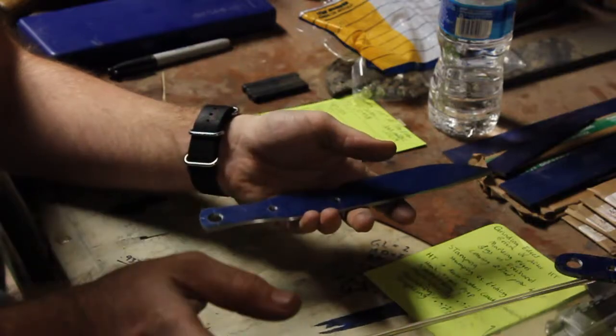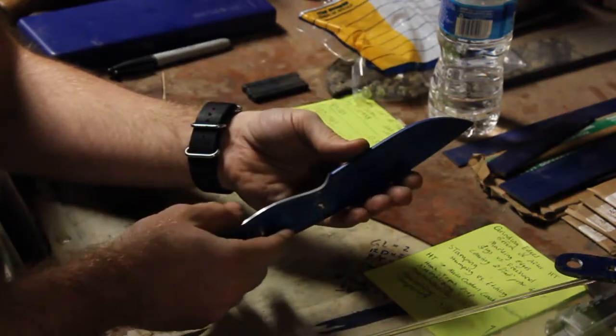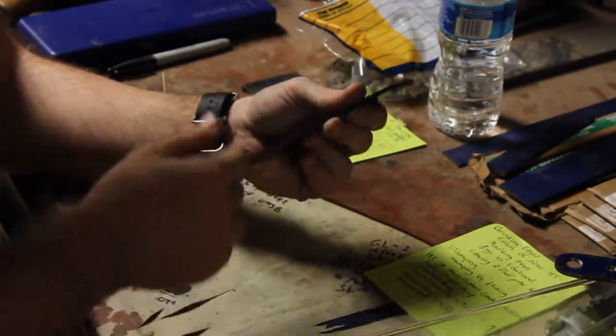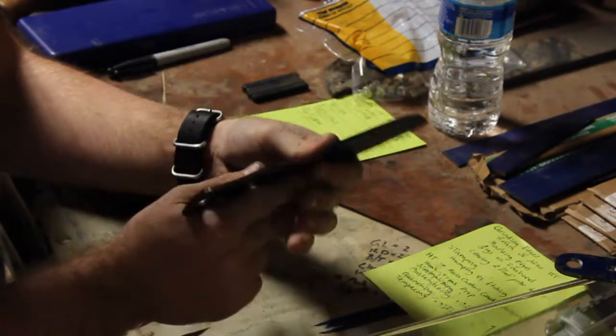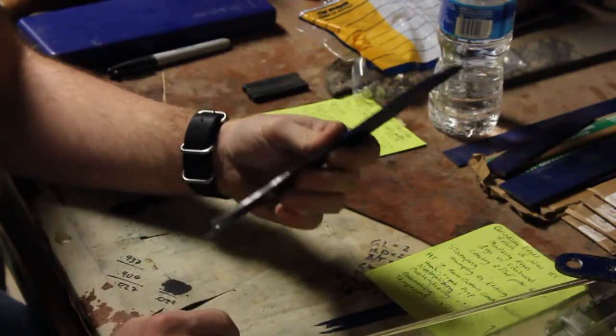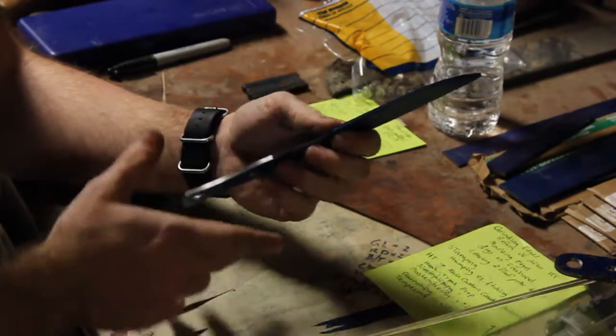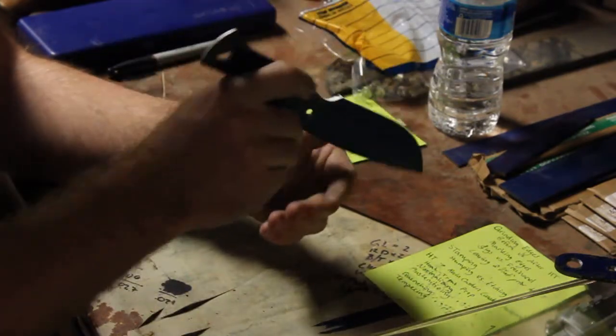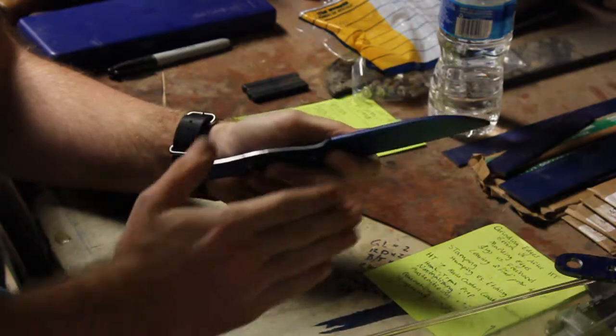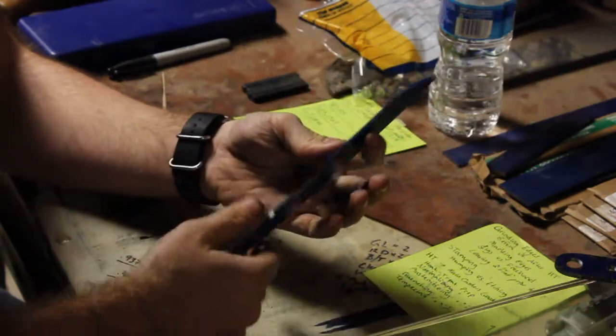Grinding after heat treat is also harder on your belts, by the way. Grinding your edges before heat treat, the steel is softer, so it's easier on your belts. However, you cannot grind it to an edge. If you grind it all the way to an edge and then you pull it out of your kiln and dunk it in your quench tank, the chances of you warping that edge go way, way up.